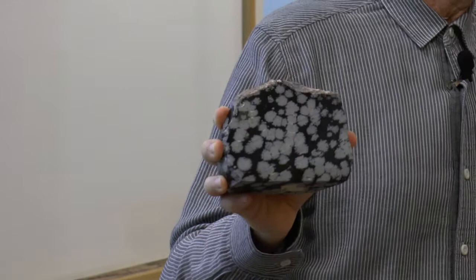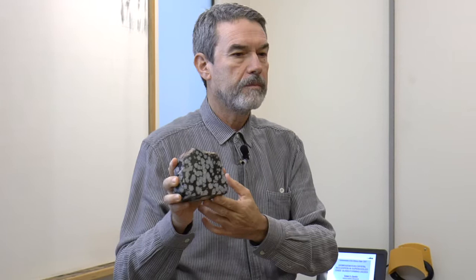On the other hand, if somebody wants to make a glass ceramic, if you are interested in producing a material with crystals dispersed in the interior of a glass sample, you have to be able to induce copious crystallization in the glass volume, in the glass interior. And then, by controlling the size distribution of the crystals, their volume fraction, their chemical composition, their texture, the number of different crystal phases, etc., one can then design the properties of the resulting glass ceramic.